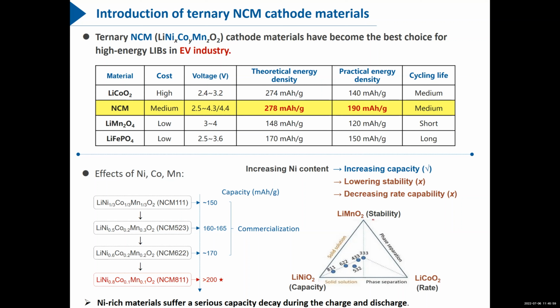Now for NCM materials, increasing the nickel content in the composition can significantly increase the capacity. For example, if we increase the nickel content to 80%, the obtained NCM 811 could have a capacity as high as 200. But this kind of nickel-rich material suffers a serious capacity decay during charge and discharge.